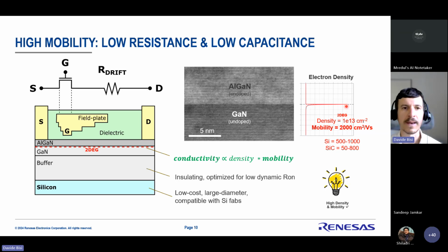As you know, it's the two-dimensional electron gas with a very high density, 1E13 charge, and with an extraordinary mobility, which is 2000 centimeters squared per volt per second. And the mobility is very high because it's a very high quality interface with no doping and no scattering. For comparison, silicon mobility is around 500 to 1000, and silicon carbide is between 50 to 800. So having a high mobility channel is the first reason why GaN has a lower resistance for the same chip area. So that's number one, a very important fact.